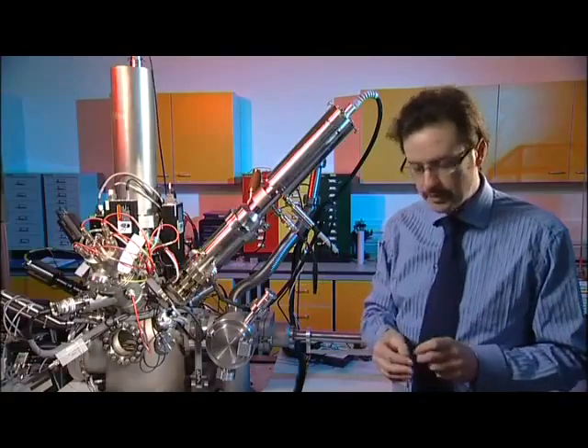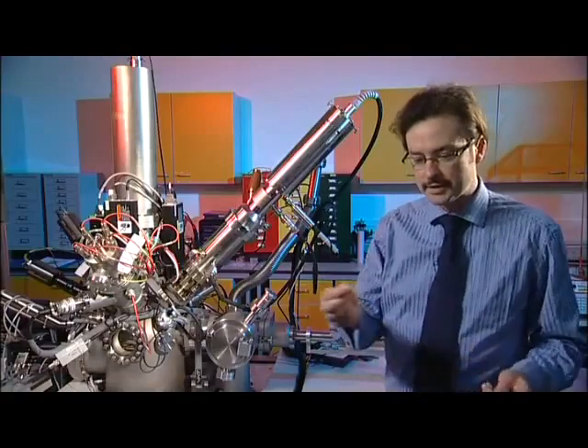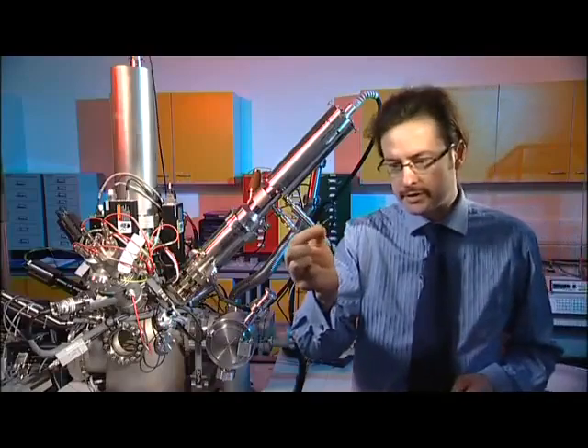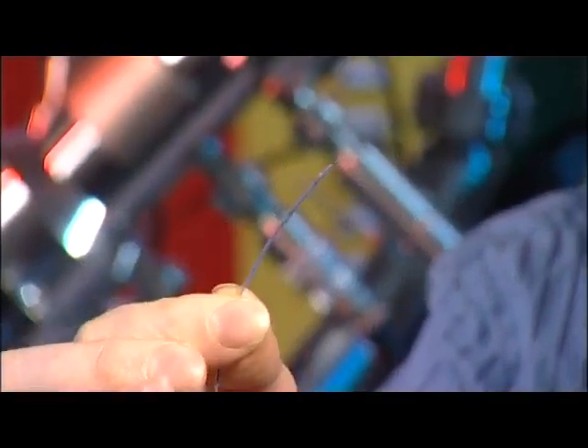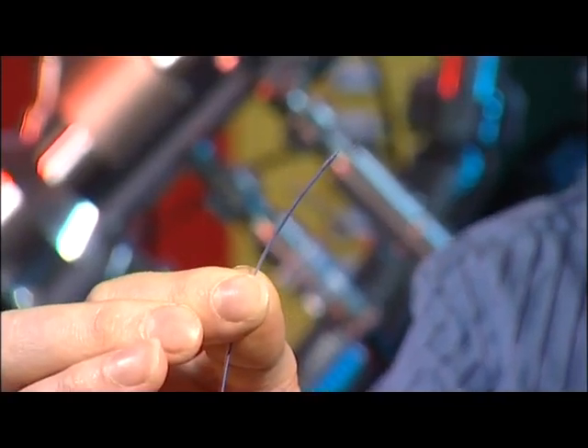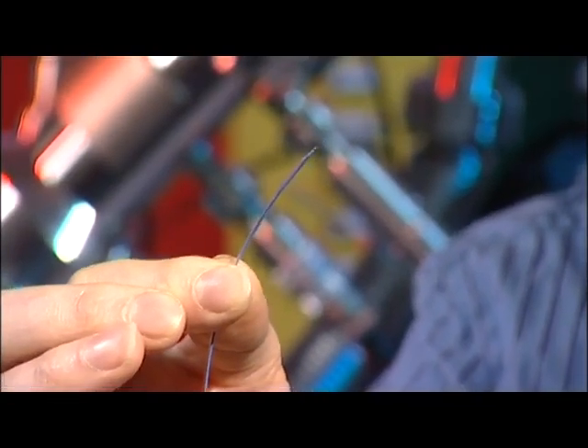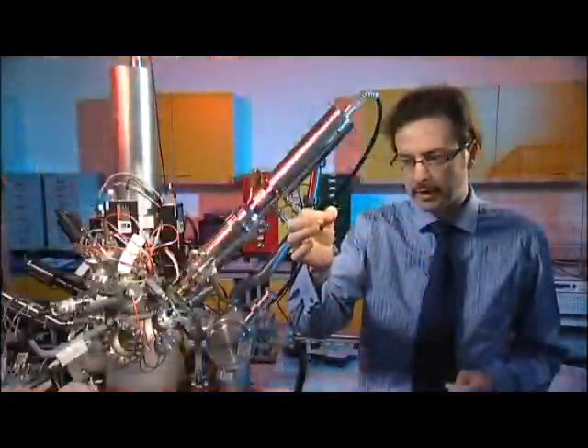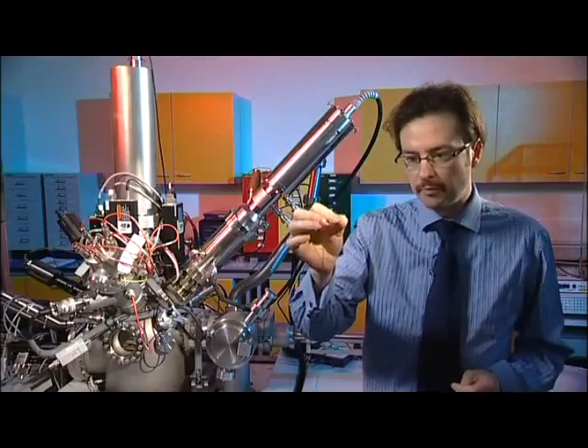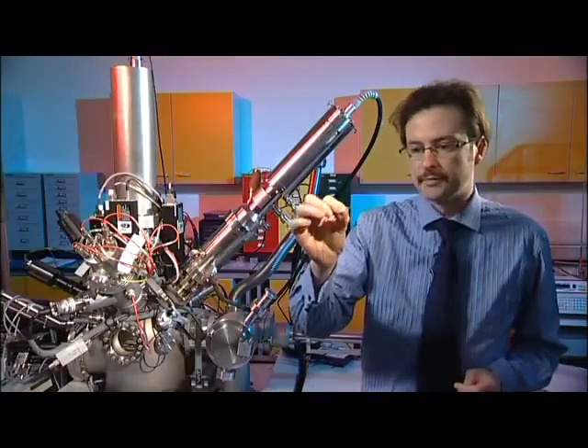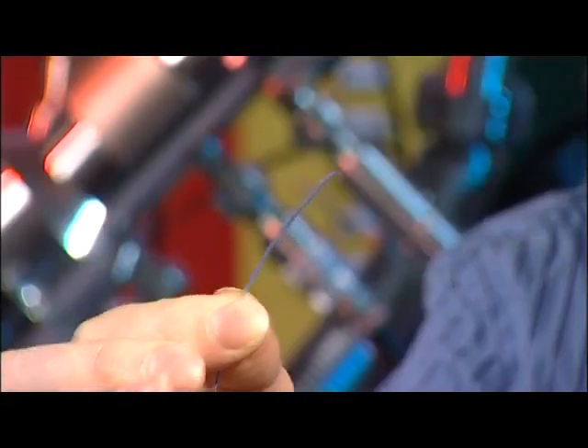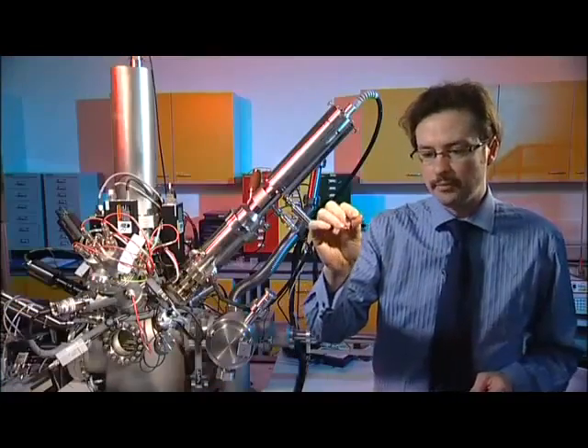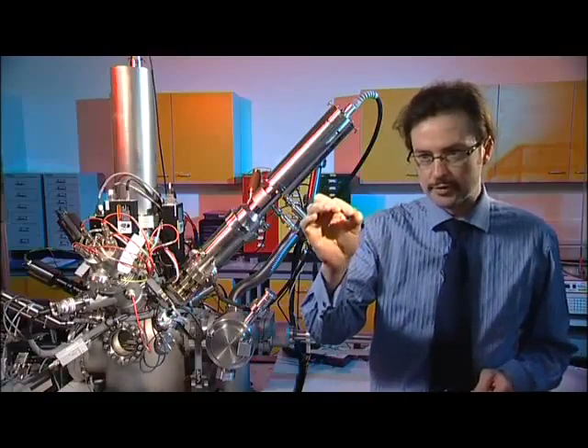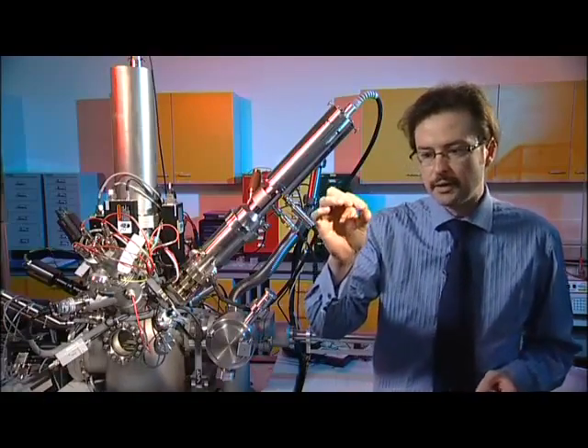So for instance, if we look at an arterial stent, this is a device here, you can see just at the very end of that there's a metal mesh. And when the surgeon places that in the artery, this is inflated by a little balloon. This is removed, leaving the metal mesh, the stent, in place. When body fluids start to go along that, then things like collagen can build up, starting to block the stent. So smart devices now have a polymeric layer which is loaded with a drug which tries to reduce these effects.